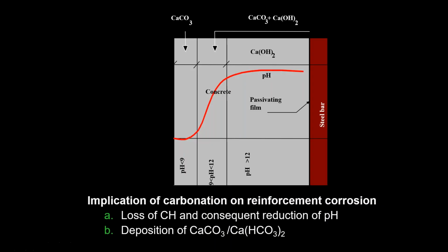You can see that on the surface the pH could be less than 9. Near the reinforcing steel, normally it will be around 11 to 13. If it goes below 9, then this passive layer will get dissolved, and then you will get the corrosion problem.